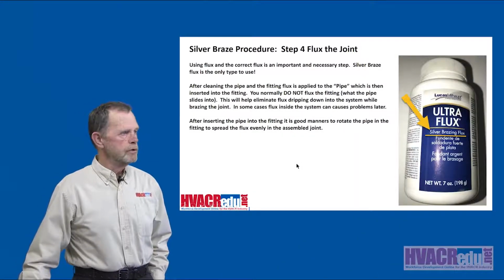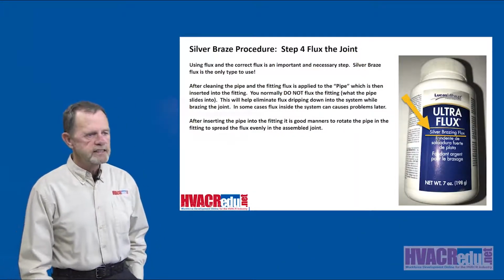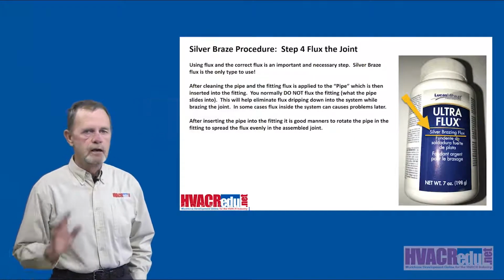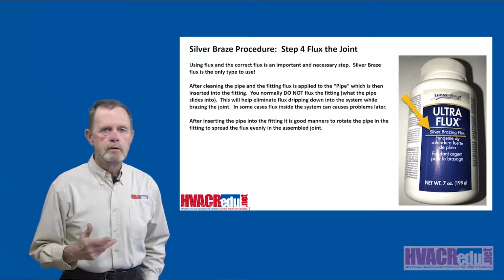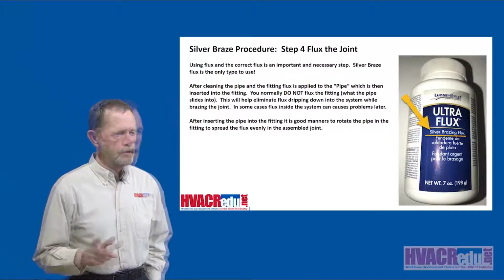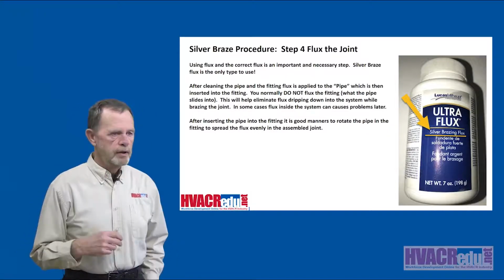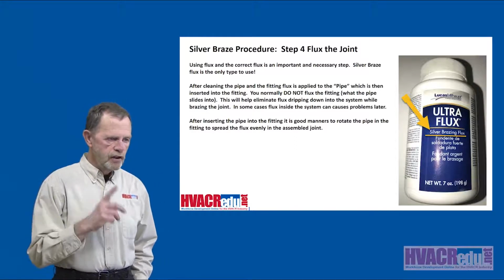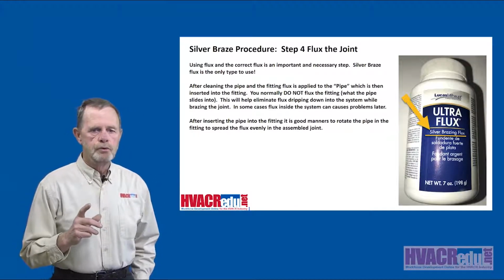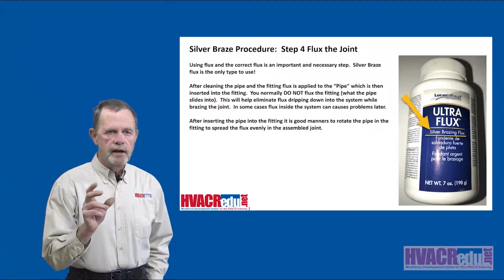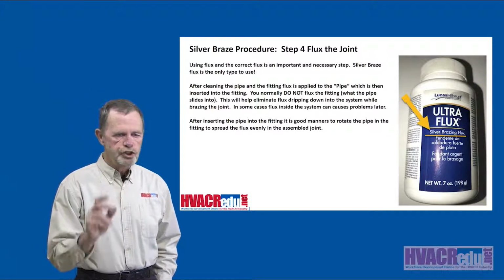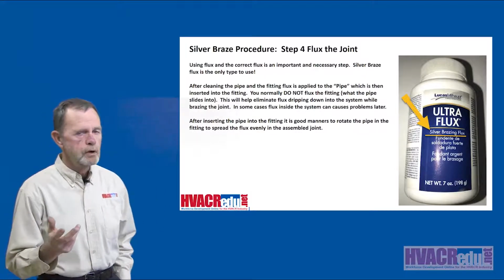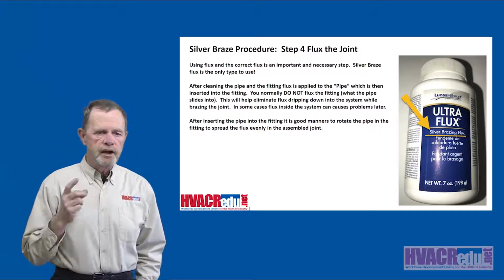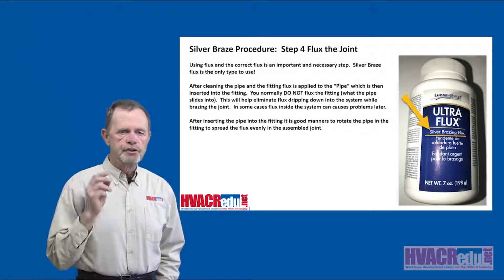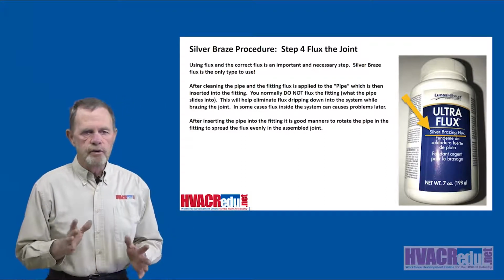And the flux is important. As I mentioned before, it has to say silver brazing flux. If it doesn't say that, don't use it. It's not going to work. Silver brazing flux. And remember from previous sessions, maybe on soft solder, the flux is designed to shield that deoxidized copper that you shined up and filed and did everything else to. And the flux is there to protect that copper from oxidization until you get to the temperature adequate for, in this case, silver braze. That's what the flux is for.